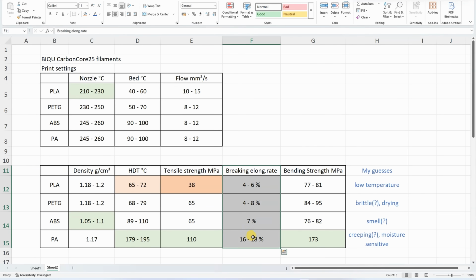This is the breaking elongation rate, a very high value for the PA. This means it will stretch quite a lot before the break. And this is the bending strength, again the highest rate from the PA or nylon. This is PA12, I have that information, which is less sensitive to moisture compared to the PA6. But usually the PLA has quite a big bending strength. This will be measured too.